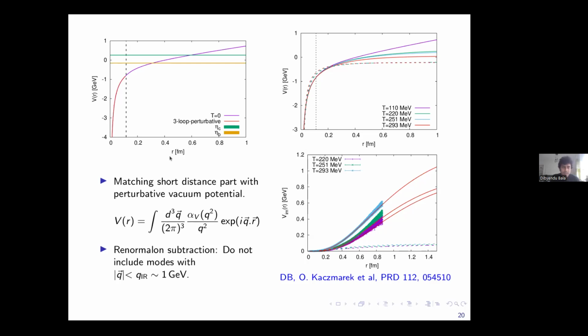But there is another issue, because this perturbative calculation will include all kinds of momentum modes when we take the Fourier transform of the coupling divided by q squared. The mode which is near lambda QCD will give you a lot of contribution, and that is a well known problem, because there is a renormalon in the potential coming from those modes. We have to subtract this renormalon, and the way we subtract it is we do not include those modes at all. Then we can calculate the potential, which can match the lattice very smoothly, and that also fixes the arbitrary additive constant on the lattice. So we can use this zero temperature perturbative calculation to remove these modes.